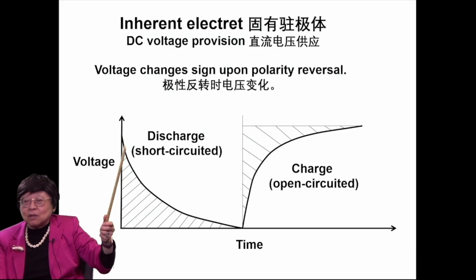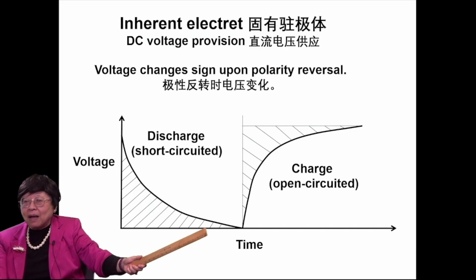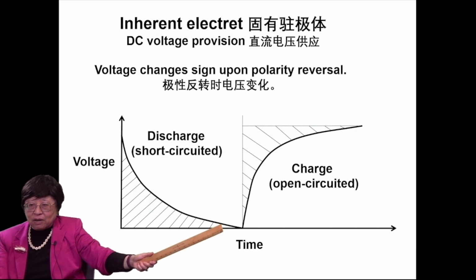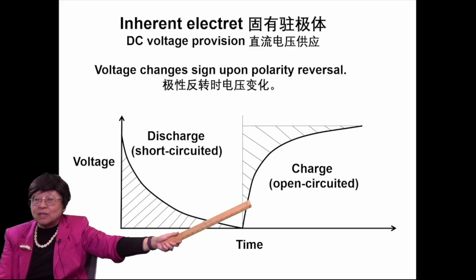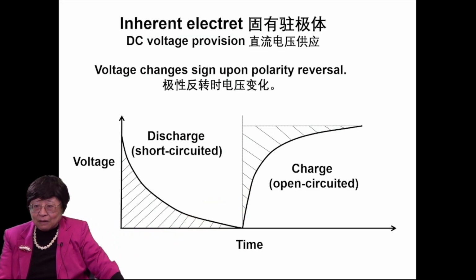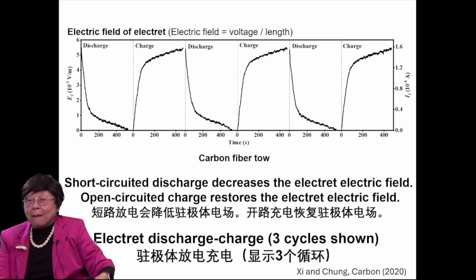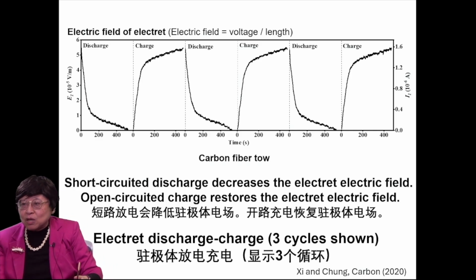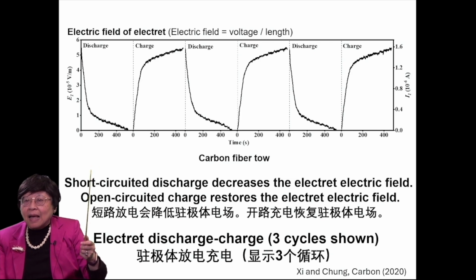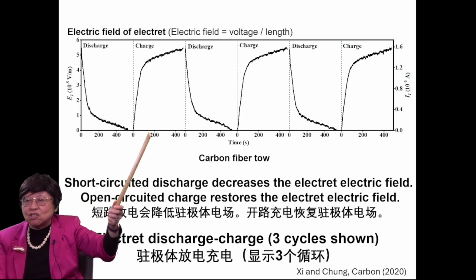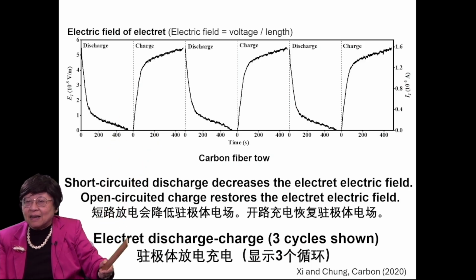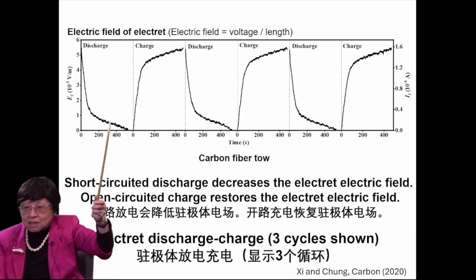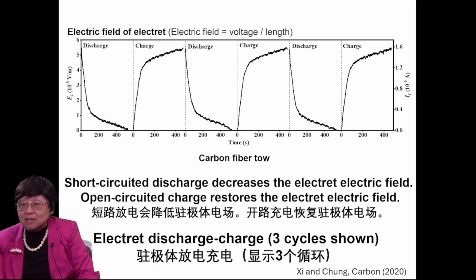And this voltage would diminish to 0 upon short circuiting. That's discharge. And then afterward, if you open circuit it, it charges back. That's self-charge. And this is for the case of carbon fiber tow, uncoated, and 3 cycles of discharge charge. So it's very reproducible from cycle to cycle. You have short-circuited discharge and afterward open-circuited self-charge.